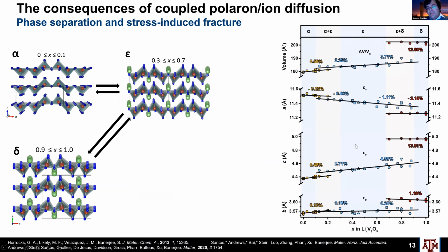This is a phase diagram that Justin Andrews has collected from really vast amounts of literature. So really data-dense phase diagrams showing the changes in volume and changes in the a, b, c lattice parameters. And there's lots to see here, but in the interest of time, I just want to draw your attention to these extended phase stability